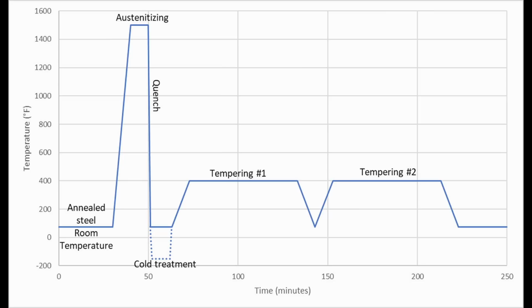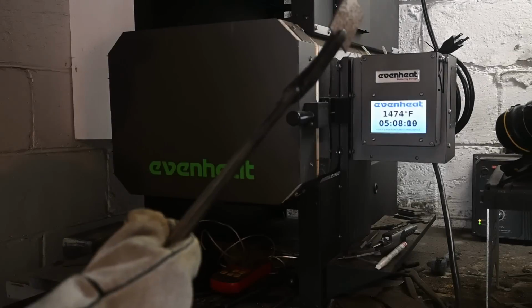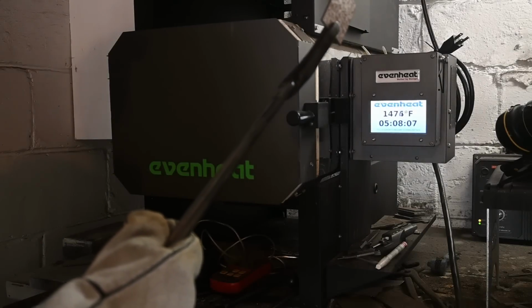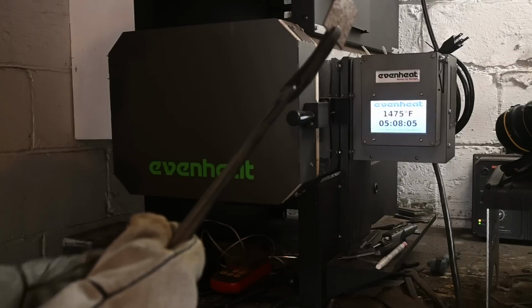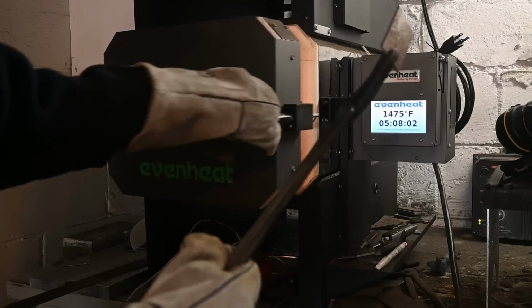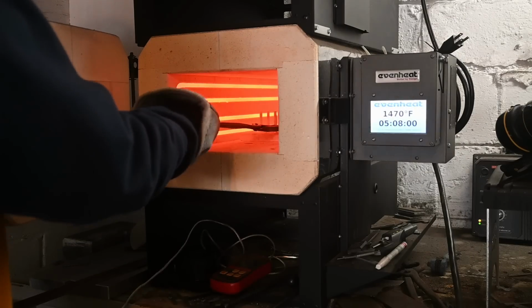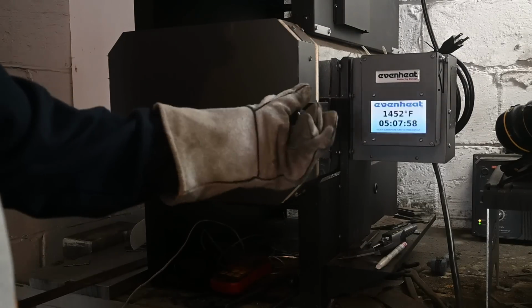So austenitizing, when we're heating up between something like 1450 to 2250 Fahrenheit, depending on the steel and the target hardness, which would be about 785 to 1230 Celsius. So you need a specialized furnace to do this. The biggest difference between small batch heat treating done by an individual custom knife maker and a factory is the size of the furnace. So knife makers usually use a benchtop unit such as those made by Evenheat or Paragon. So the number of knives that are in the furnace is usually much greater in a factory furnace.